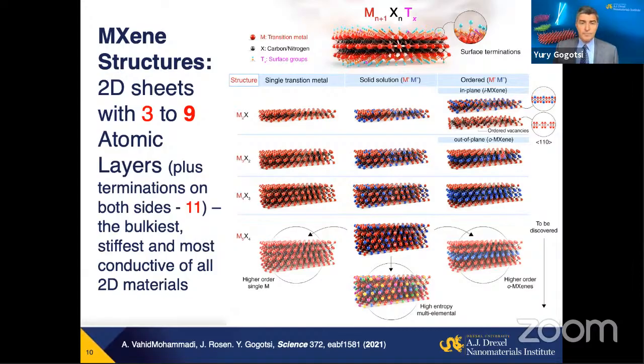We also have materials which are atomic sandwiches. We can have one transition metal on the surface and another transition metal in the middle, where the chemical, electrochemical, catalytic and other properties of the surface will be determined by the transition metal on the surface, for example, molybdenum. And electronic and transport properties will largely be determined by the transition metal in the middle, like titanium.